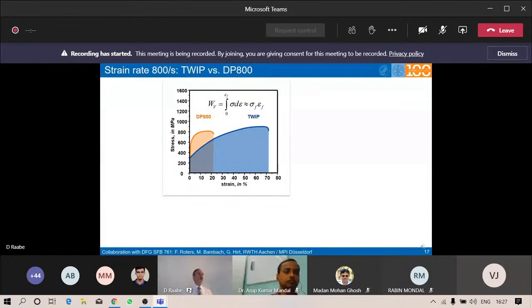Let me jump back from the atomic scale or microstructure scale into the macroscopic engineering scale. Here you see now a very engineering test where you see the two flow curves, one for DP800, so a dual phase steel with 800 UTS, and a TWIP steel. TWIP stands for twinning induced plasticity. And you see the two vastly different stress strain curves.